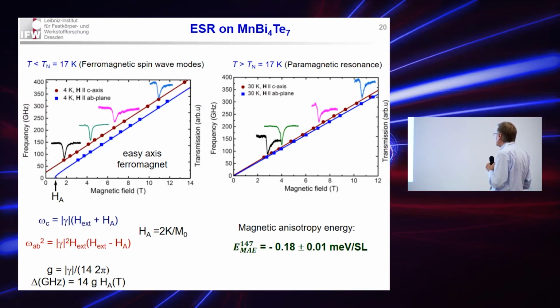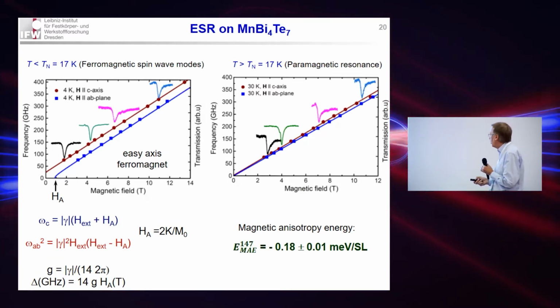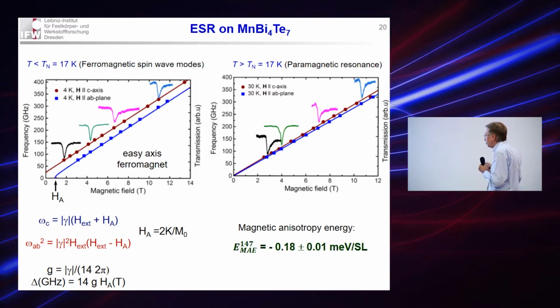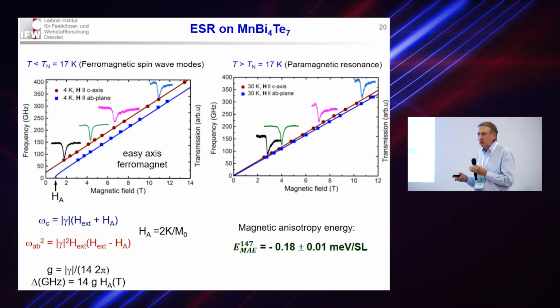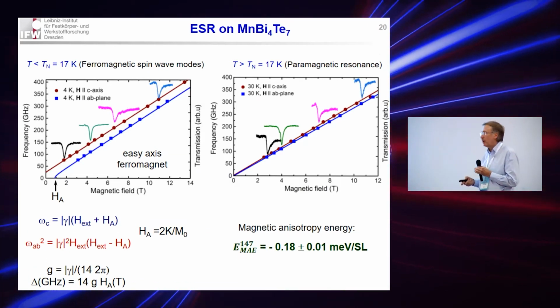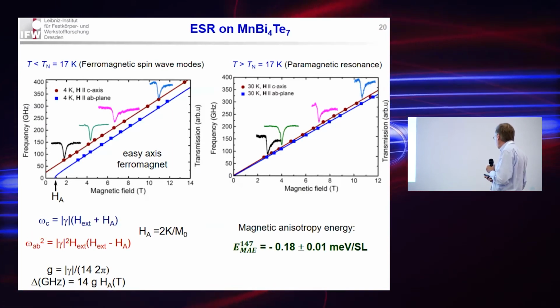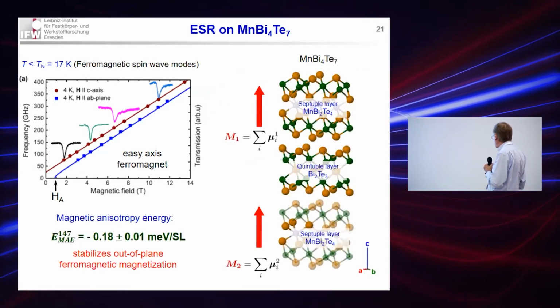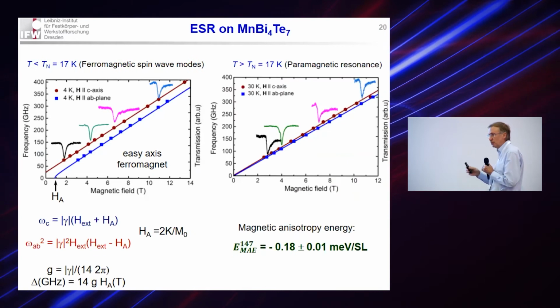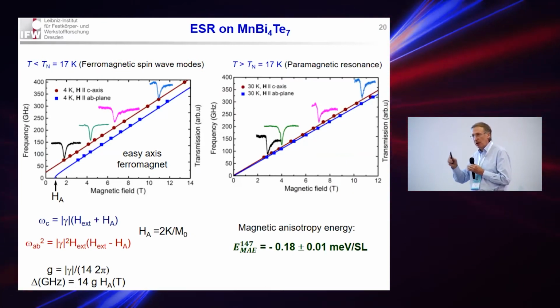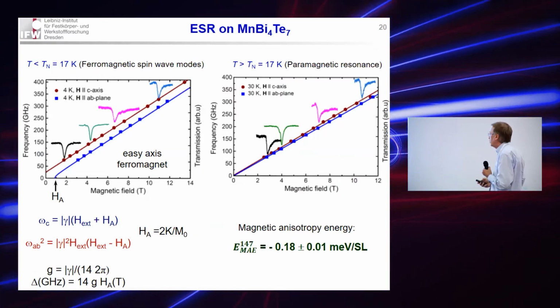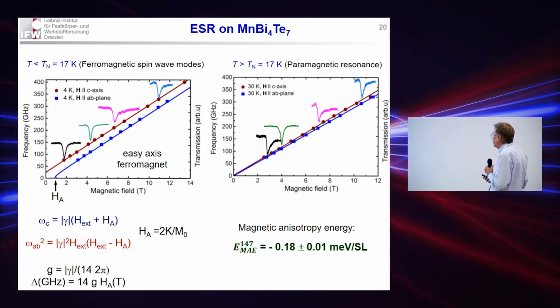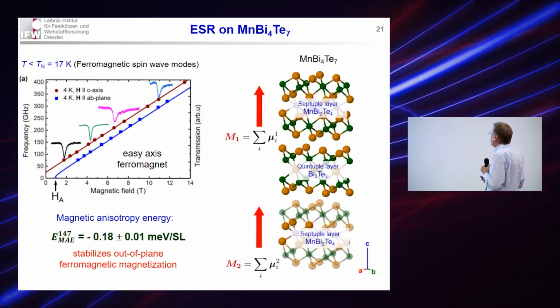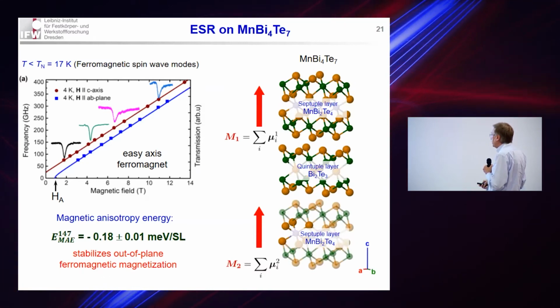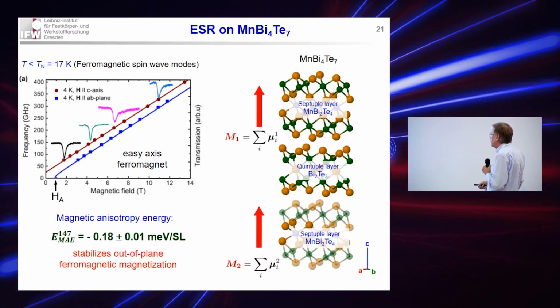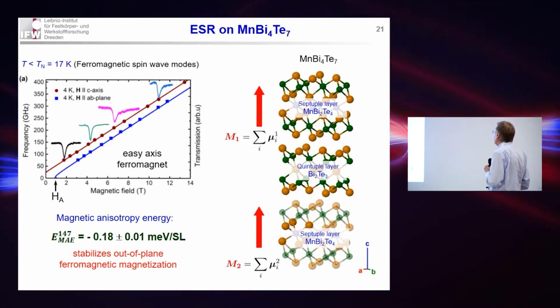It's a number, minus about 0.2 milli-electron volts per magnetic layer. Actually, it's just a number, so why should it be so important? One important thing that we can justify: it is indeed a minus sign, that means this is out-of-plane anisotropy, so the magnetization prefers to stay out of the plane, which is needed to make a gap at the Dirac cones. So that means it stabilizes this out-of-plane ferromagnetic magnetization.